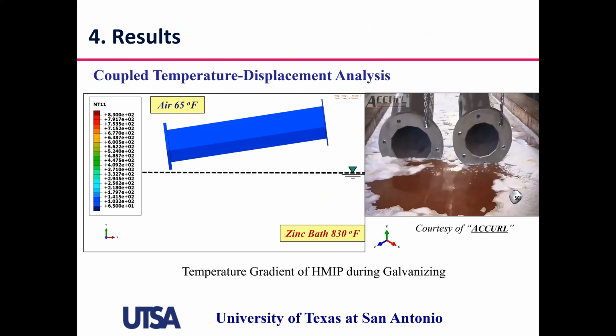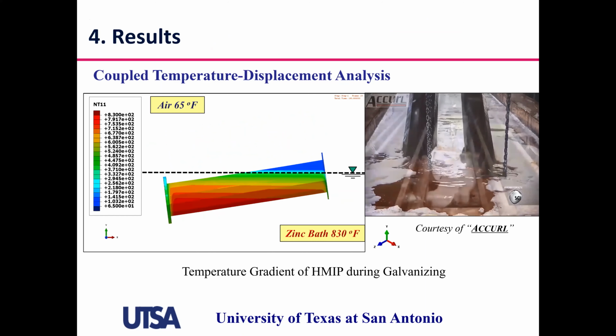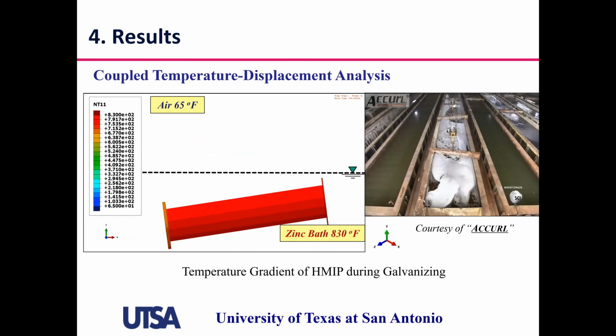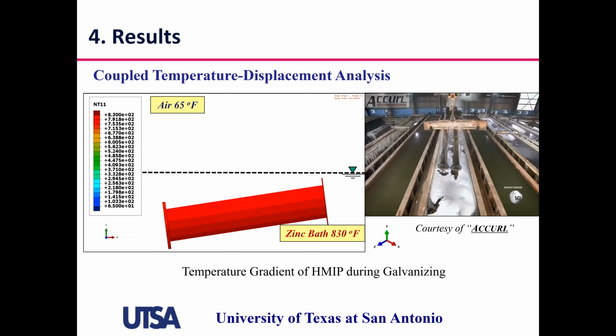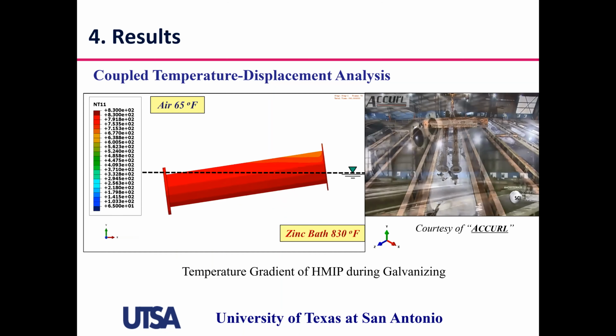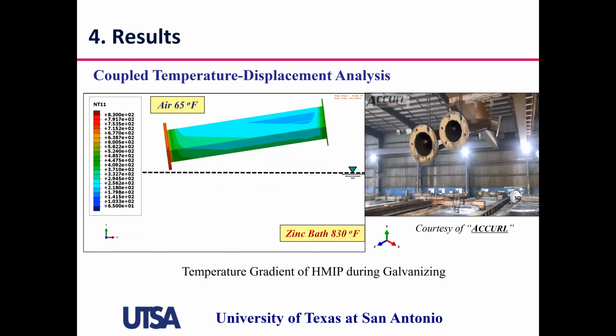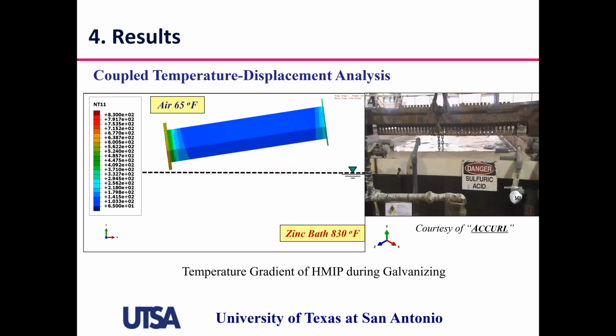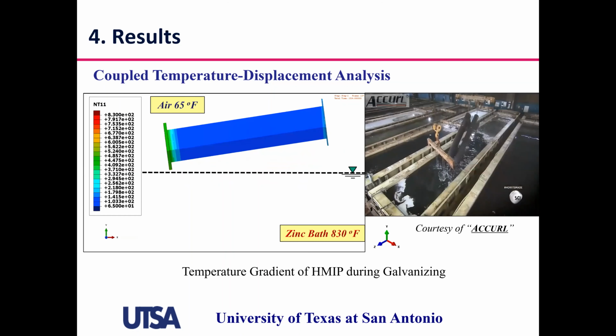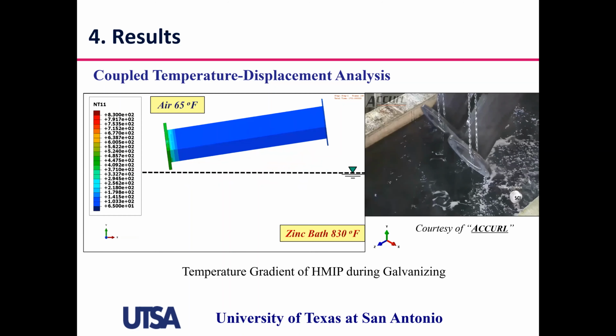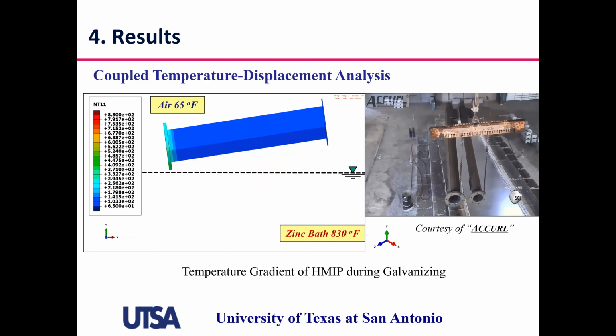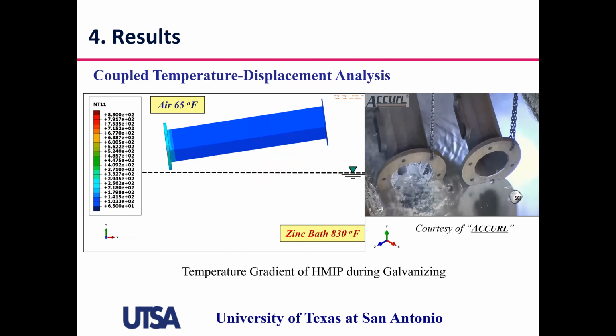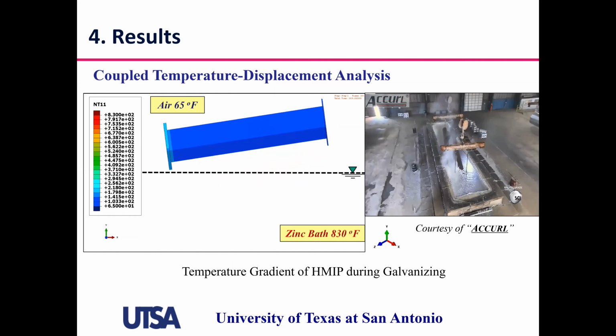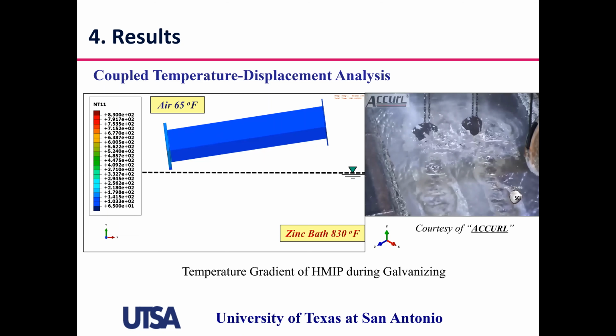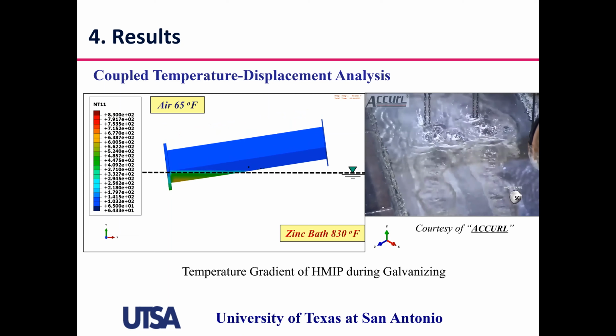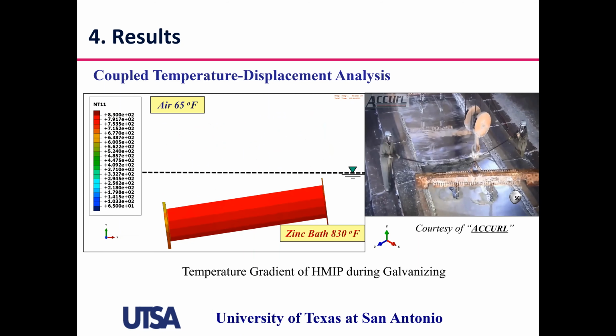So these are some results of our simulation, where we're trying to capture the bath process. So we created some user routines in Abaqus to be able to mimic this galvanizing. And here you can see as you submerge the high mast illumination pole into the zinc bath, the temperature changes quite rapidly, and then you extract it, and then the structure starts cooling down, as you can see here. So we were able to calibrate our model with some experimental results that were available for early stages of the simulation. There were some thermocouples there that we were able to have good agreement with.